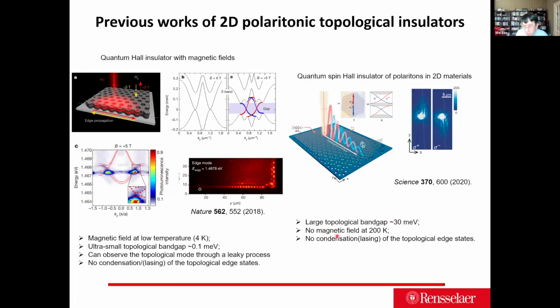And there's no magnetic field because they use a quantum spin Hall effect in the photonic design. However, there's also no condensation or lasing of the topological edge state, simply because of the poor optical performance of the 2D material. They tend to have really low quantum yield and are not so reproducible, even the ones that report polariton condensate. Those samples are typically very hard to make.